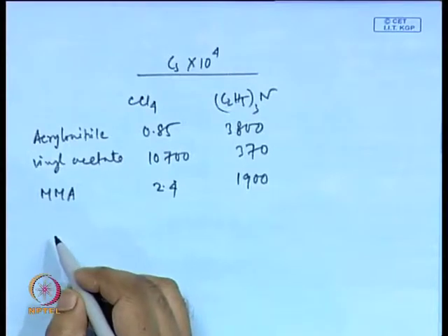Now, if you found in your reactions a very high molecular weight which you do not want, then what you can do is use chain transfer agents. Now, what would be good chain transfer agents which can easily participate in chain transfer reactions? Molecules like sulfides and thiol containing compounds.